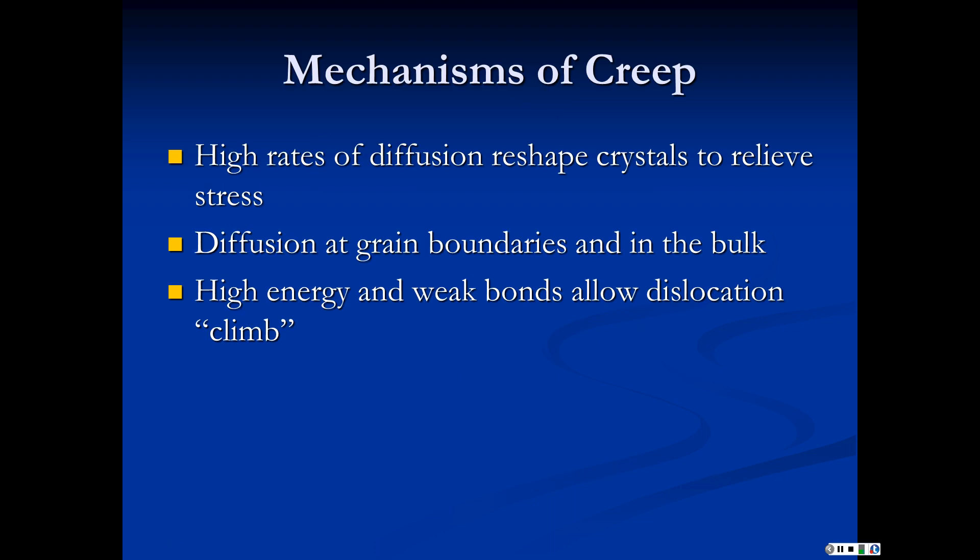There are really several different things that contribute to creep. It's quite complicated. You get very high rates of diffusion that allows crystals to reshape to reduce their strain energy. They're relieving the stress. Diffusion of grain boundaries and in the bulk is going to feed this. You're also going to have dislocations doing stuff they couldn't do at normal temperatures because the high energy present in the weak bonds at high temperatures will allow dislocations to climb and move around things that blocked them before.